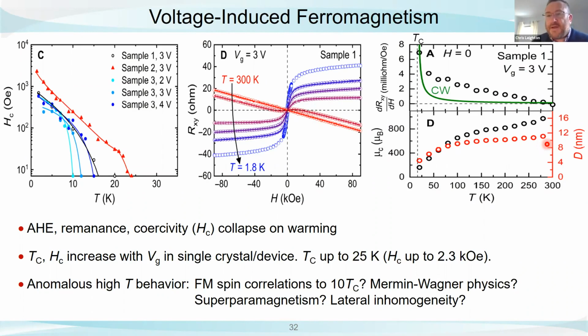Can we use something as a protective layer? That's a really fantastic question. I know of one piece of work that's been done along these lines. David Goldhaber-Gordon's group at Stanford has developed a technique to put some micron scale, very thin hexagonal boron nitride flakes in between a target material and an electrolyte. And he did that to boost mobility, but I think this is a potential way to moderate the electric field to potentially avoid the kind of damage that you're asking about. Are there other methods to do that? There are, and actually we are trying some chemical means to deposit very thin films that would not necessarily be 2D materials that could perhaps be scaled a bit bigger laterally. So that is research that's ongoing.